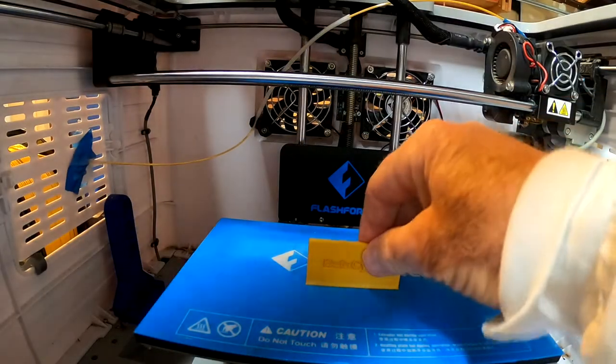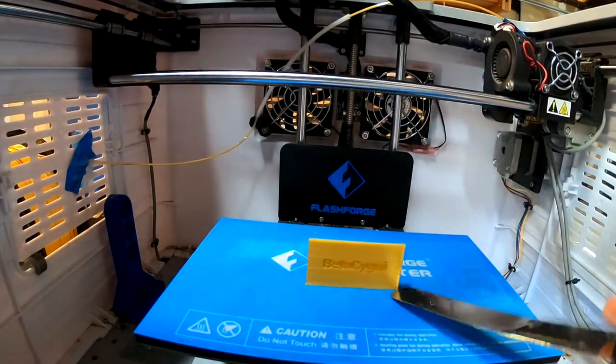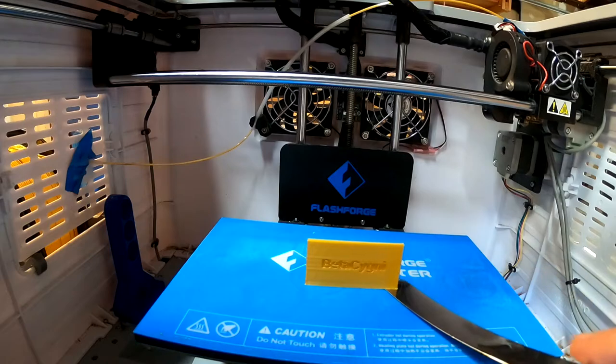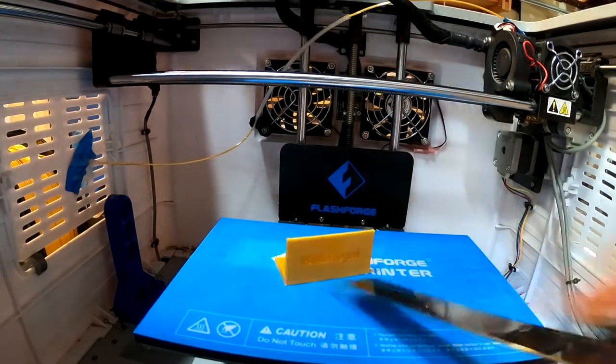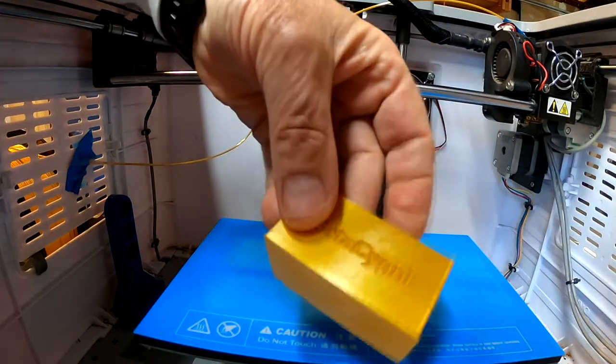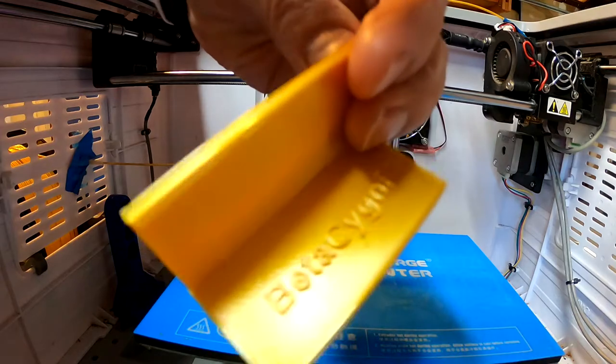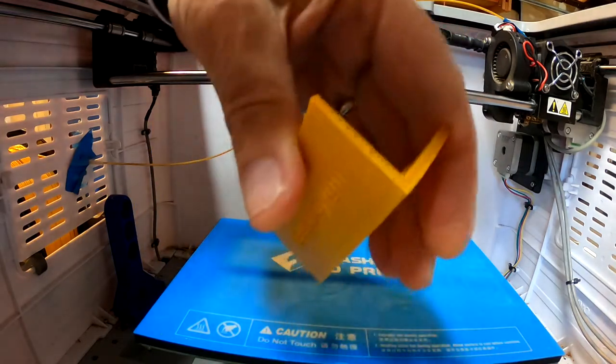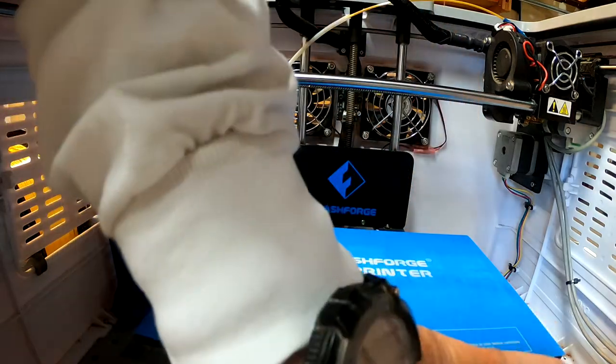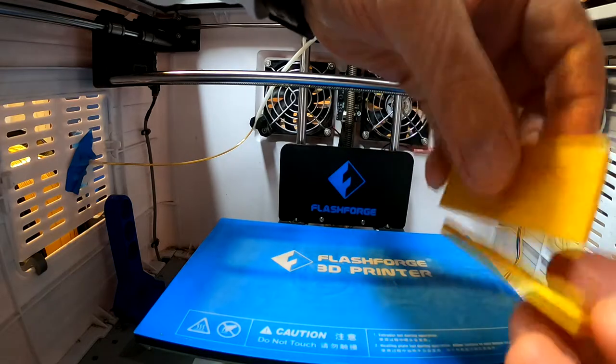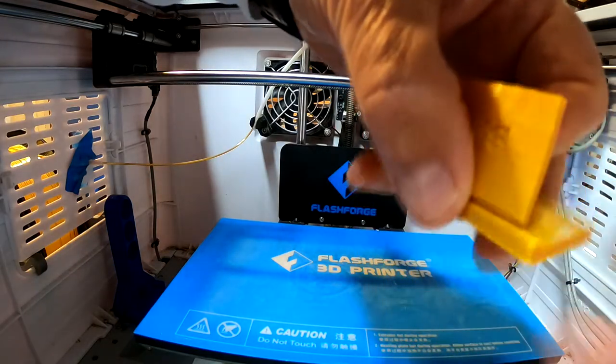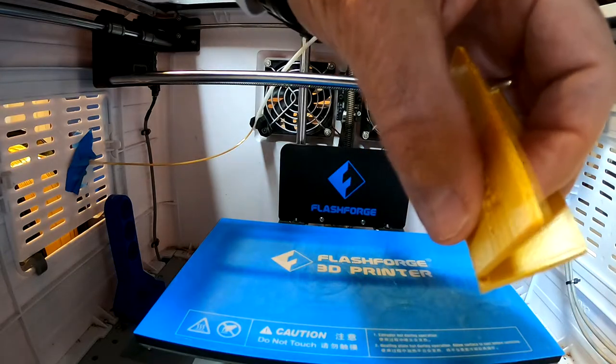It looks like it turned out well. It's pretty solid. Let's check the bed adhesion. Bed adhesion is good. I'd say it's solid. Bottom came out clean. Surface is nice and shiny, and this is nice and shiny because it's not blobby at all, so it wasn't being overheated. Strength-wise, well, it was pretty strong. Not quite as strong as I thought, but for what I'm printing, it's not that critical. I think we had good layer adhesion, not quite as good as some of the other filaments we've used, but I think the layer adhesion is fine.